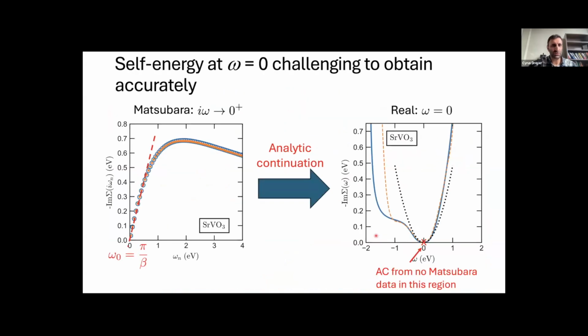But of course, as many of you know, obtaining low energy properties of the self-energy to high accuracy is very challenging. And the reason is, well, there are several reasons for this. One reason is that we're usually doing our calculations on the Matsubara axis, and therefore, depending on the temperature at which we do the calculation, we have some low energy regime where we have no data points. We have a lowest Matsubara frequency, and below that we have no data points, and so we need to do this extrapolation to 0 frequency.